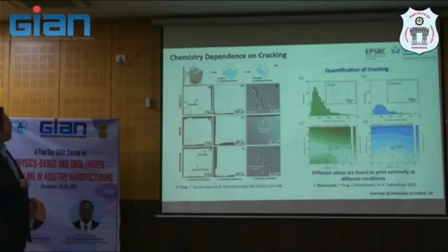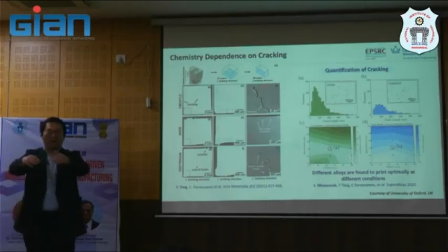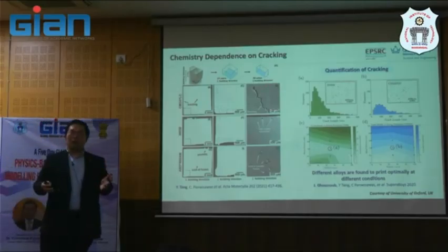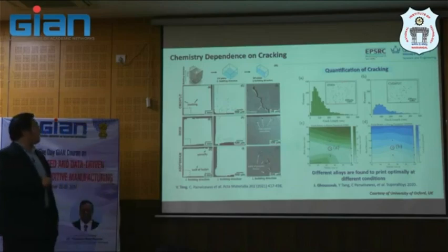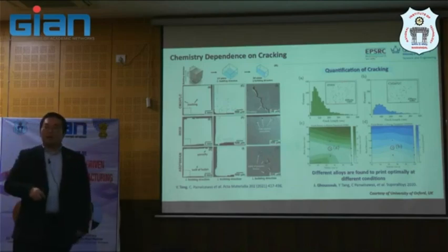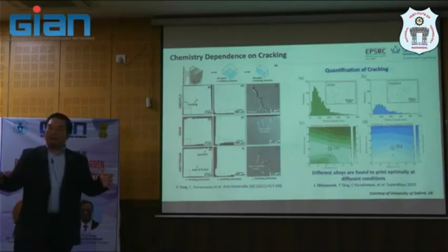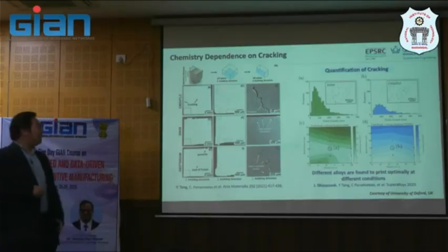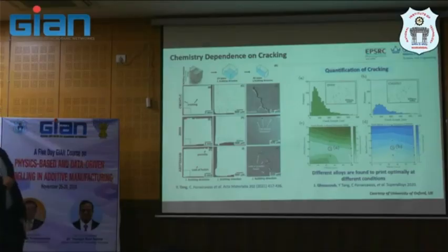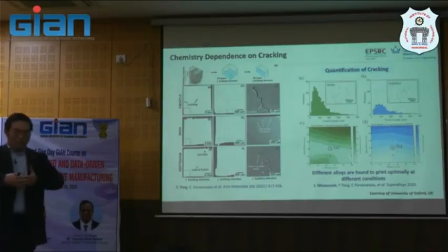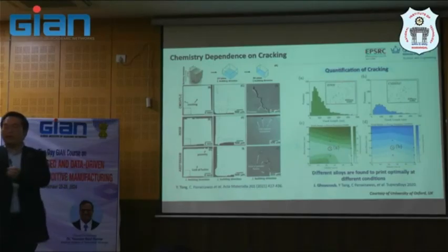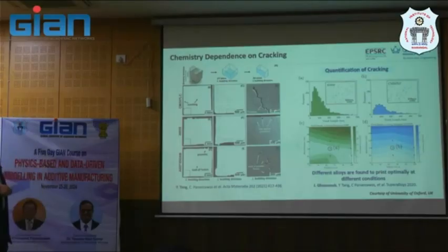But what we did is we map, using a mosaic kind of approach from OM, optical micrograph, and SEM, across this 10 by 10 millimeter. It's a huge area. Usually people will not do this, but that is what we found: the crack at the edge is related to the different, I would say, heat transfer coefficients between the edge and the bulk, and that means you get different structure. But anyway, at the edge and in the bulk, we call it micro and macro cracking here. And that is why we always show the edge.